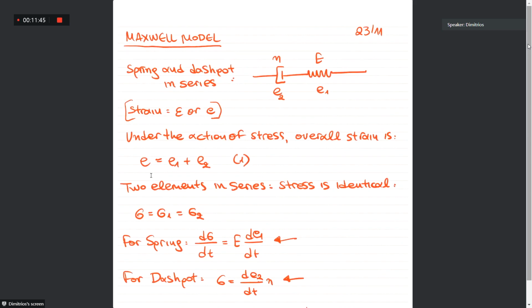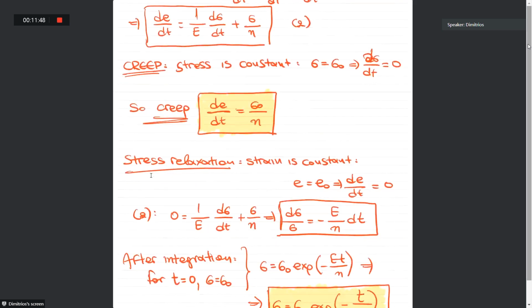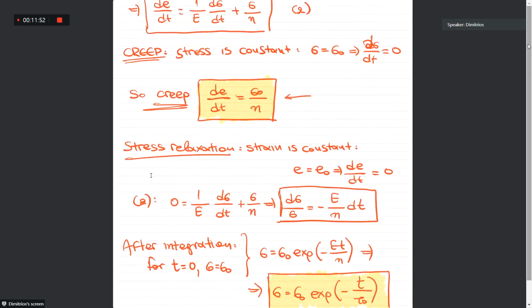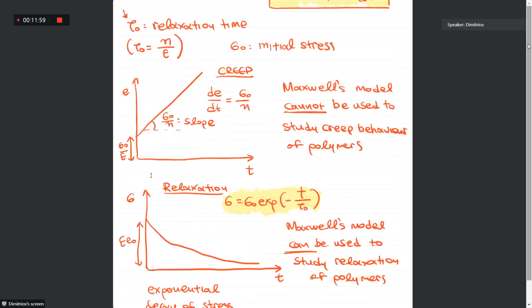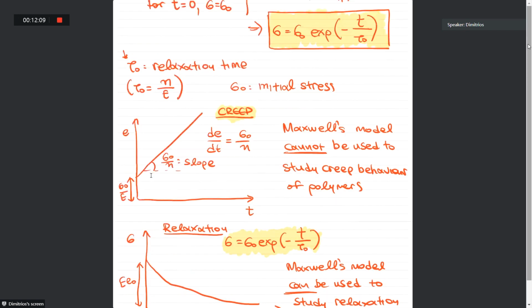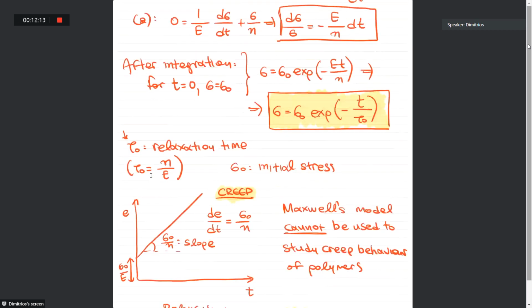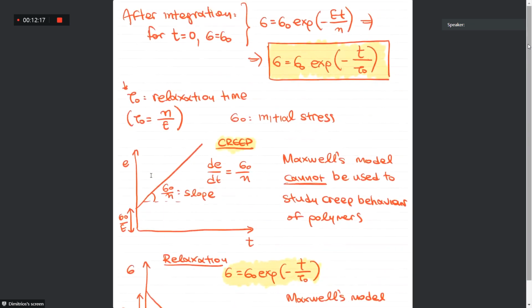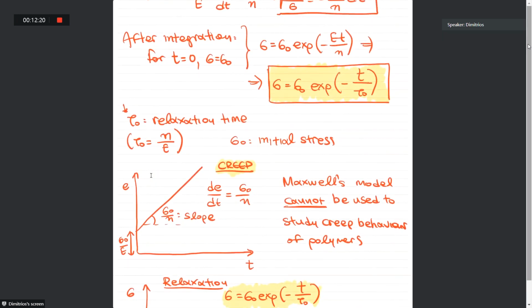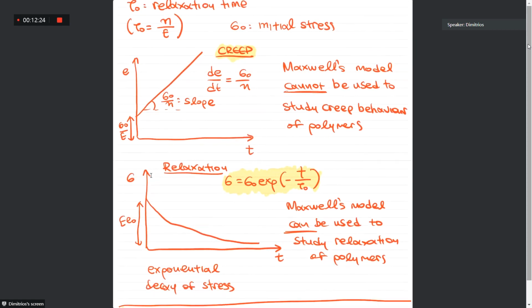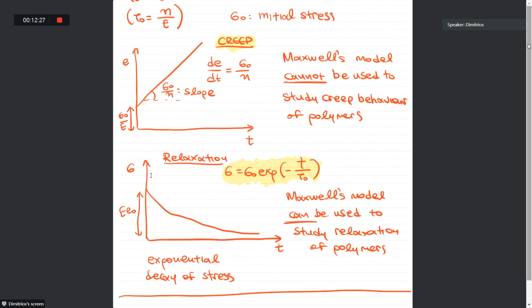And we went through our notes, and as we can see, for the Maxwell model, we obtain this equation for the creep behavior, which, as we understood, cannot describe the creep behavior, because you can see that the ultimate graph for the creep behavior based on Maxwell's model is this one. So it cannot be used to study the creep behavior of polymers. While in terms of the stress relaxation, we can see that the Maxwell model is very useful, because it can be quite accurately used to study the relaxation of polymers, okay?